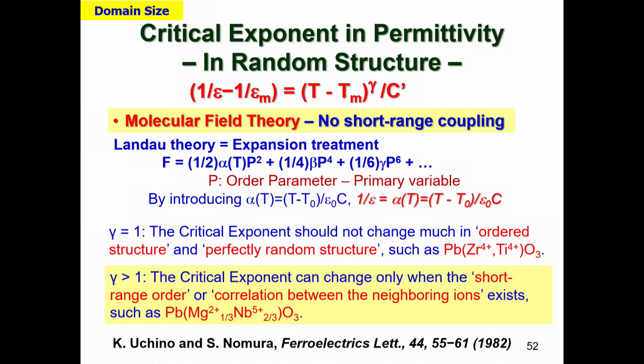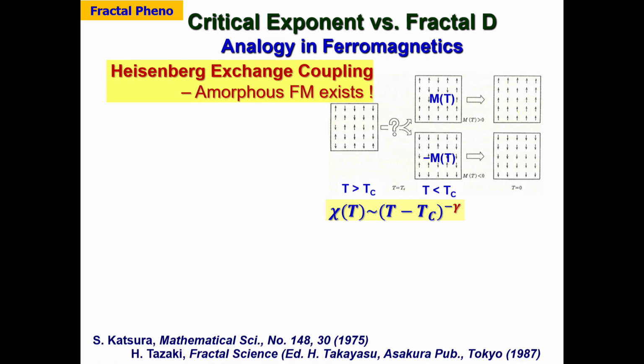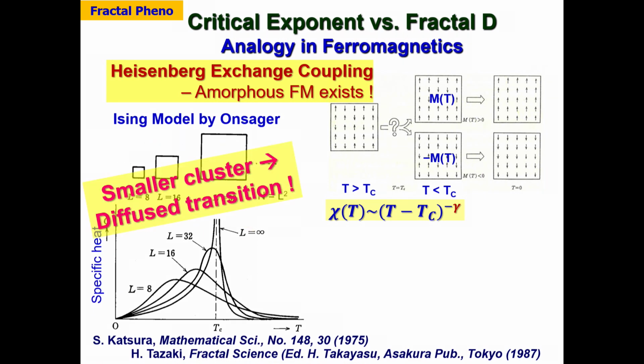Gamma is higher than 1. The critical exponent can change only when short-range order or correlation between the neighboring ions exists, such as in PMN, okay? So the ordered cluster and the disordered cluster both exist. Unfortunately, in ferroelectrics, the fractal dimension and this critical exponent correlation has not been completely clarified yet. So I will show you just an analogy from ferromagnetics, due to the lack of time, just showing the final result.